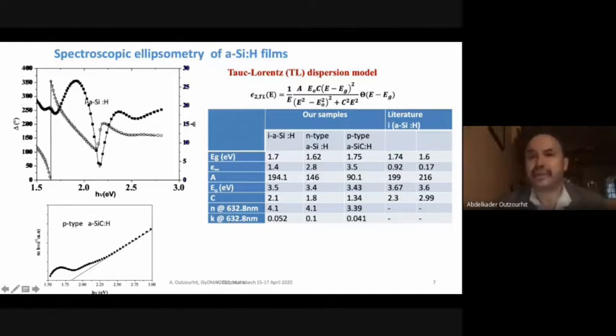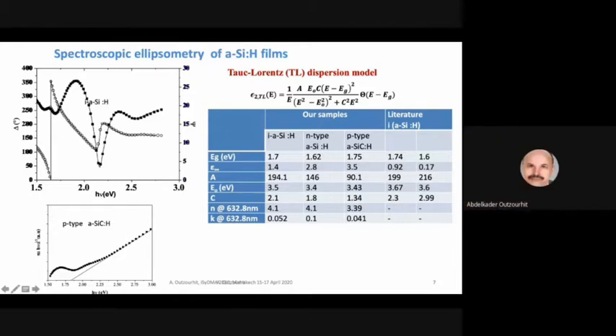Okay, I also here presented some of the values that were obtained from literature. As you can see, the band gap here varies between 1.74 and 1.6 for the intrinsic amorphous silicon. And as you know, this parameter or the characteristic of the films generally depends on the deposition conditions, and mainly the flow rates of the various precursor gases, the temperature of the substrate, the RF power, of course, and also the pressure within the deposition chamber. There are other parameters of the models. Also, they agree with the experimental ones obtained from the literature.